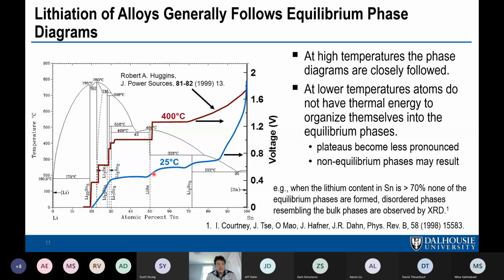And the reason is because you're in a two-phase region, and from the Gibbs phase rule, if we're a two-component system and we're holding temperature and pressure constant, then we don't have any more degrees of freedom. So as long as we have the two-phase coexistence, the potential can't change, and so it reaches a plateau. So anytime you see a voltage plateau in a two-phase system, it's a good indication that you're in a two-phase region. As you continue to lithiate, you enter another two-phase region, and so on, and at 400 degrees C it pretty much follows the equilibrium phase diagram. At 25 degrees Celsius, you can see it kind of does too, but things get more smeared out, especially over here when you have a lot of lithium and you're reaching the end, the fully lithiated state.